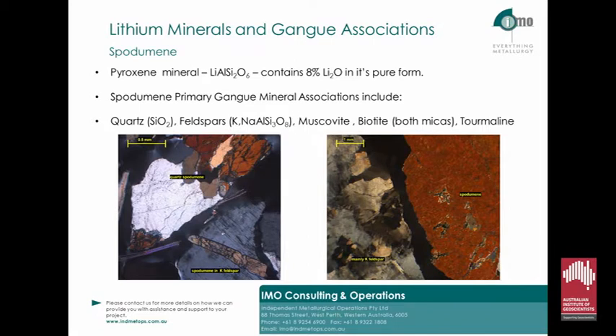If the mineral characterisation and test work is not done properly up front, operators may not potentially achieve their recovery targets. Spodumene is typically coarsely liberated, enabling producers and budding explorers to produce a coarse high-grade product from a relatively coarse upfront gravity circuit, which exploits the specific gravity difference, which generally ranges from 0.4 to 0.6 grams per cubic centimetre between the spodumene and the gangue minerals. Whilst the gravity circuit will produce a coarse, relatively pure spodumene product and a rejects fraction with minimal spodumene and primarily gangue minerals, it will also produce a middlings fraction, which consists of lower grade spodumene and gangue mineral composites, which require further downstream processing by grinding, gravity, flotation, and magnetic separation.